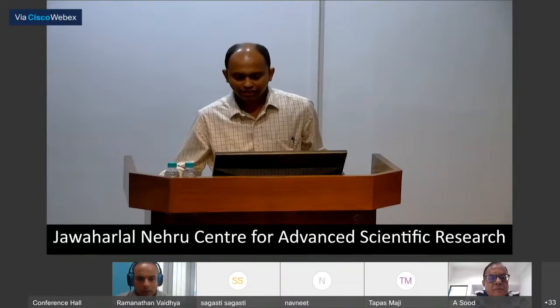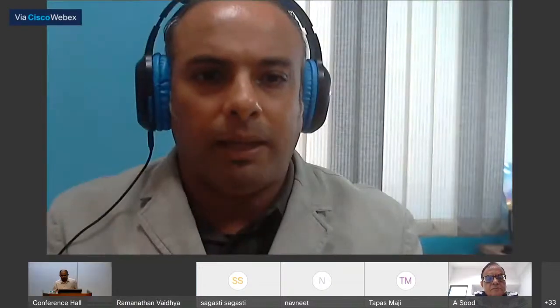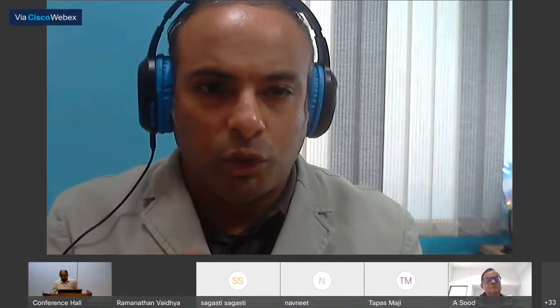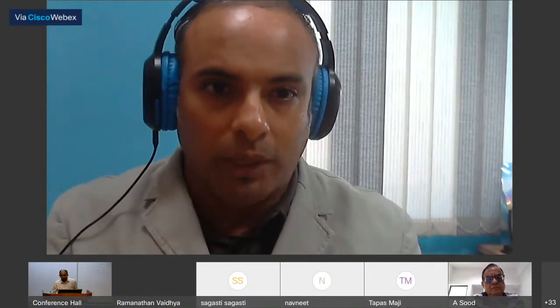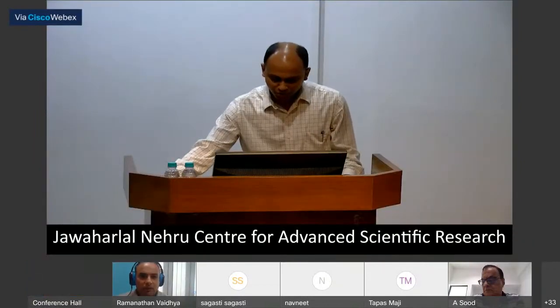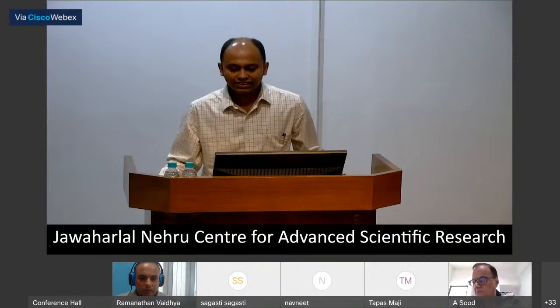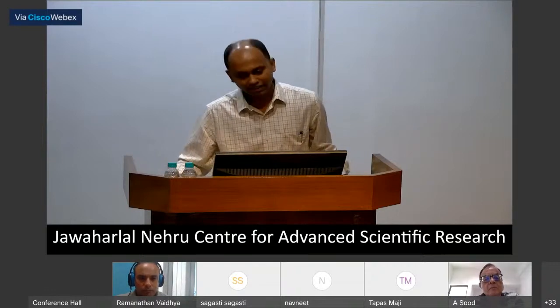I have one different way to look at this. I looked at your diffraction patterns, particularly the electron diffraction, where you get these supercells, and you see these four spots around the main spot. Typically such things also happen when a structure grows as a twinned crystal lattice. I know this, twinning. We have taken care of this during the electron diffraction, so we are aware of that crystallography.